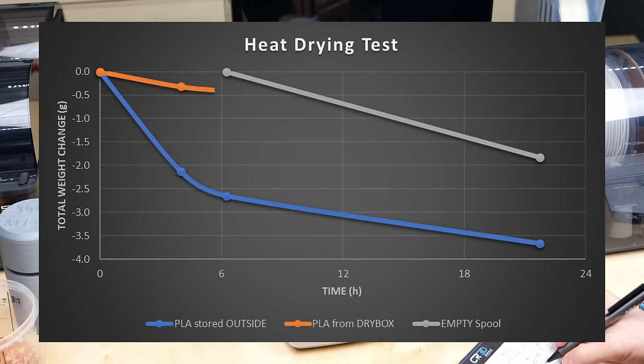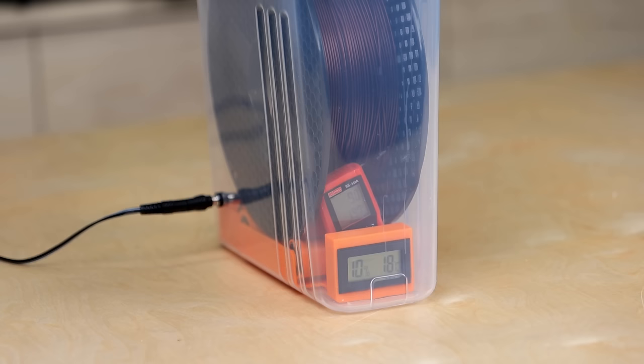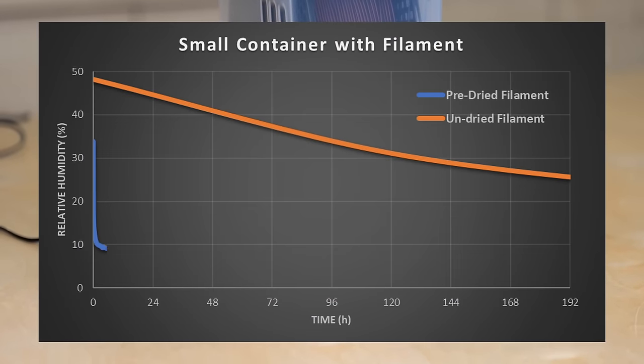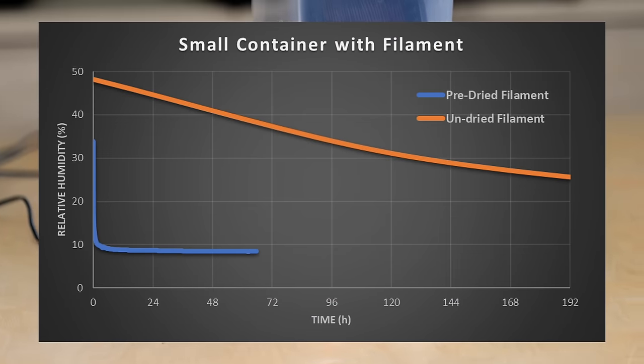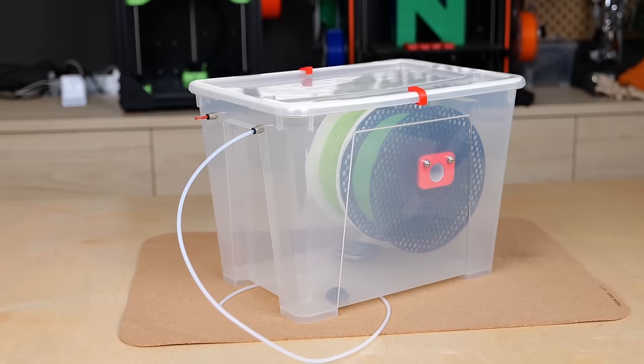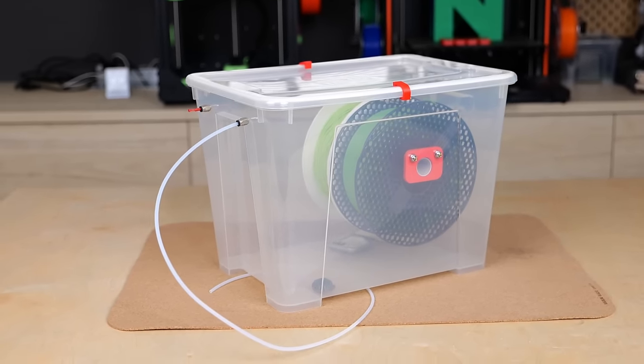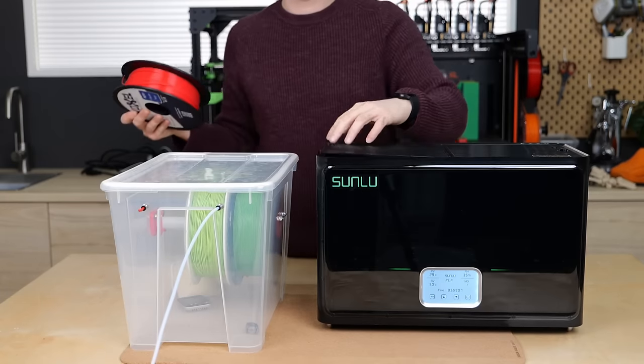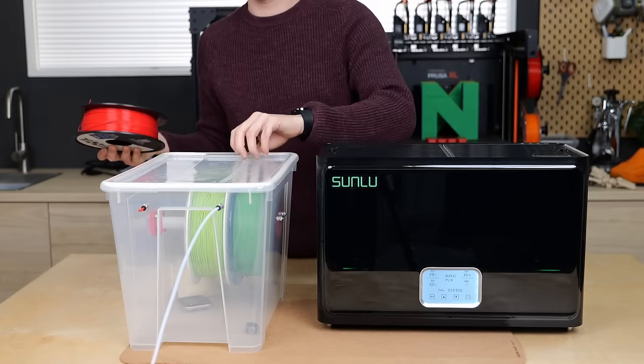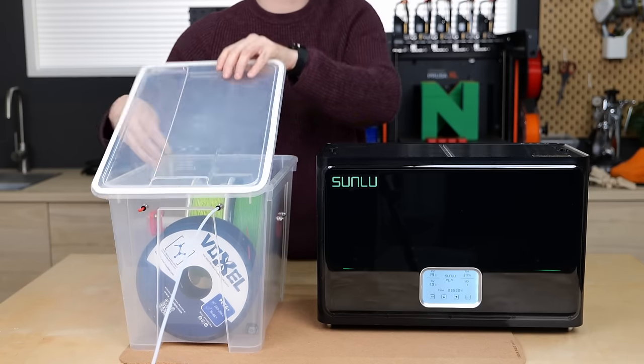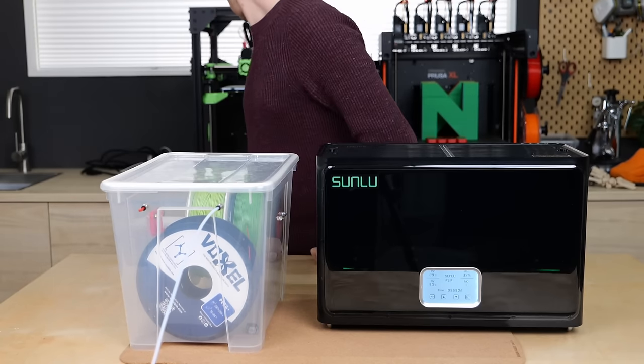When I put this dried roll of PLA back into the small dry box, the humidity level plummeted right away because there wasn't any moisture left in the spool. Lesson learned here, if you want to store filaments in a dry box, put them in there in a dried state because this will help the desiccant last longer and not potentially undry the other spools in there. The point I wanted to make here is that the first test that I made with the AMS boxes might have been nice to see, yet the humidity inside of the box is negligible compared to what the spools of filament potentially contain.